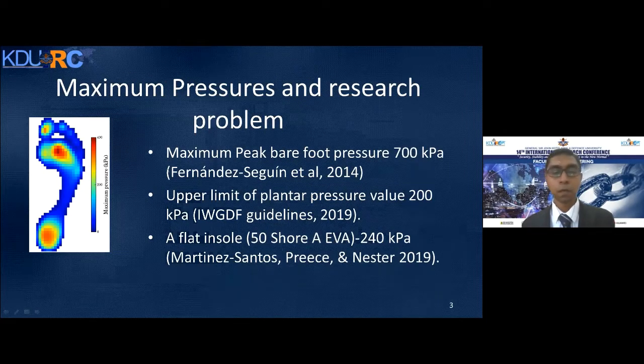The peak pressure of an average healthy person can go up to 700 kilopascal. This value is higher for patients with a history of diabetic foot ulcers. According to IWGDF guidelines, the recommended maximum pressure on the foot plantar is 200 kilopascal. But the available EVA insoles can reduce it only up to 240 kilopascal. So the aim was to introduce a material that is more suitable for patients with diabetes-related problems. But in this paper, we are presenting only the thickness optimization part of the research.